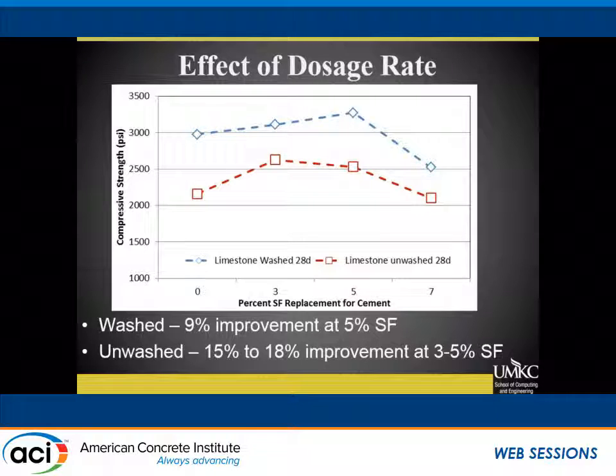We did a little bit lower dosages because we know that 10, 15, 20 didn't do us any good. And so for our washed limestone, we did see an increase in strength up to our 5%, and then at 7 it dropped off. For our unwashed limestone, really 3 to 5% was similar. Kind of interesting thing, we've always said for Pervious that you want to wash your river gravel, and limestone probably doesn't need to be washed as well because the limestone fines get incorporated into the paste. And, well, here we saw a substantial difference between washed and unwashed.